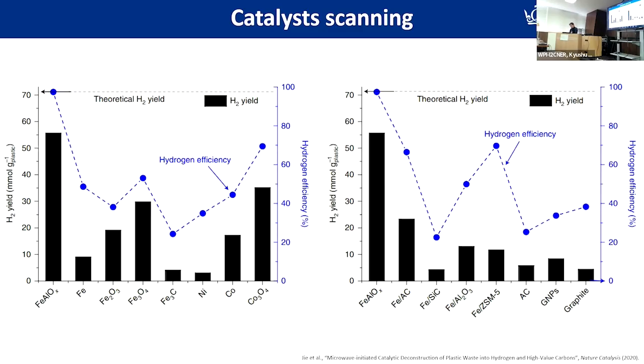And for nickel and cobalt, again, this is proposed as having good catalytic properties, but when we use it, it does not respond to microwave perfectly. In that sense, they are not working well. We also tried using iron-supported catalysts, using activated carbon, silicon carbide, and carbon alone. Again, it's not as we expected; they do not show better performance in the microwave, especially for hydrogen stripping in the microwave.